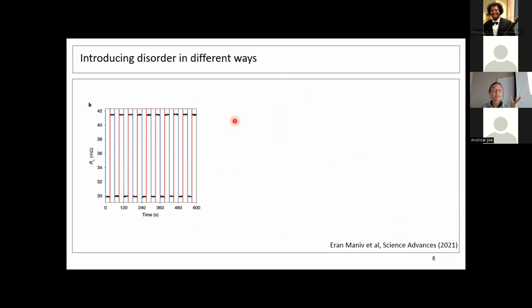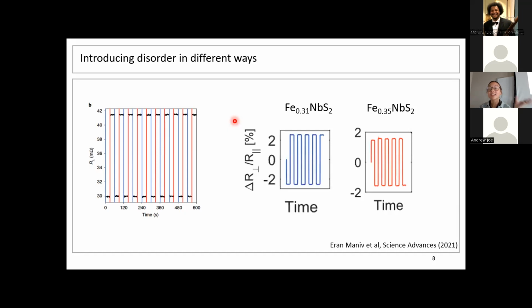Okay, so it turns out there's a hint if we look at how the switching behavior changes as we change the amount of iron in our system. If we start with our perfect triangular lattice, and now we're taking away a few iron atoms, making it a bit more disordered, versus adding a few iron atoms and making it disordered in a different way, then with the exact same setup, the exact same current pulse will bring our iron deficient samples to a low resistance state and our iron excess samples to a high resistance state. So we have basically completely opposite responses just by introducing disorder in two different ways.